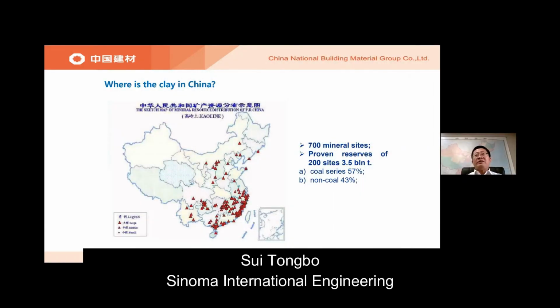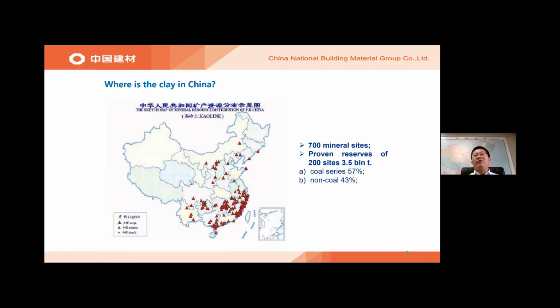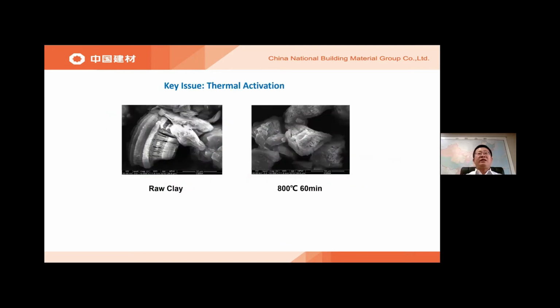And regarding the location of all these mines of kaolinite, we have roughly 3.5 billion tons of kaolinite clay, mostly located in the south and the east part. And here we see from the SEM observation that after the thermal activation, the calcined clay maintains, more or less, mostly the original morphology and structure of the raw clay.